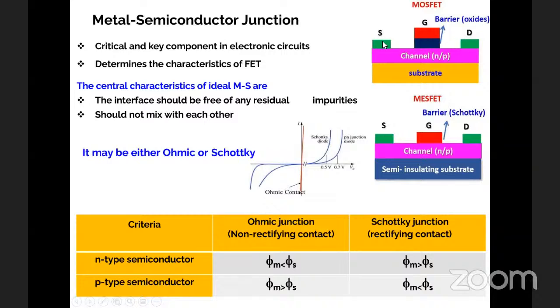So if you use the same material as the source material, then you should have a barrier material here. By appropriately choosing metals with appropriate work function, as mentioned in this criteria, you will achieve either ohmic contact or Schottky contact. So in any electronic device, there are two contacts, one ohmic and one Schottky. Ohmic contact is mandatory for transporting the electrons without any barrier, while the Schottky barrier will determine the rectification behavior or switching characteristics. In fact, the Schottky diode is almost equal to the PN junction diode, because in a PN junction diode you will see a barrier at the P-N junction. In a Schottky diode, Schottky means nothing but the metal semiconductor. But please don't confuse here.